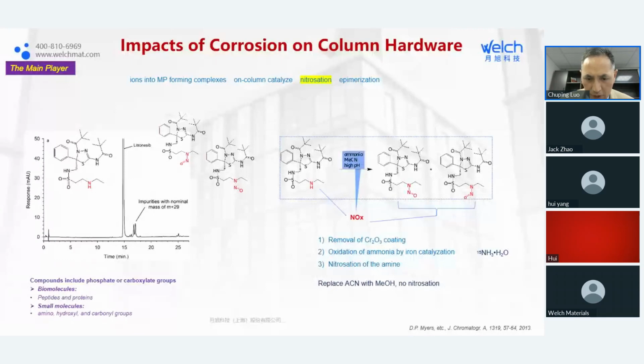How can that happen? Because in this system, ammonium and acetonitrile at pH 10 generate NOx, and NOx reacts with amine to give you the nitrosation reaction product. The experiment was designed by the people in this group, Dr. Myers, and they published it in 2013. They found that first of all, they need to remove the chromium oxide from the surface, and later the oxidation of ammonium is catalyzed by iron. So it's believed that without catalysis, this reaction is very hard to happen.